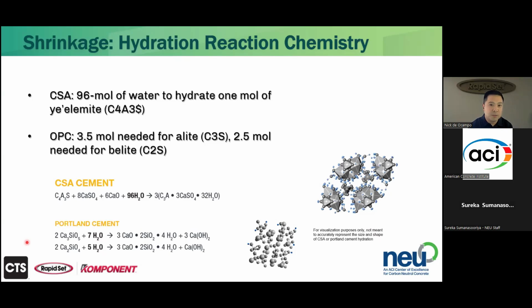Where a 0.25 is required for the Portland cement, so it's roughly twice the amount of water, but practically speaking, the water cement ratios are going to be pretty much standard at around 0.3 to 0.5, depending on what kind of slump or workability you're looking for, and of course what water reducers are being used. You can use water reducers in Portland cement to minimize the amount of free water, water of convenience, available in there to minimize that shrinkage. The same could be done for CSA cement as well.